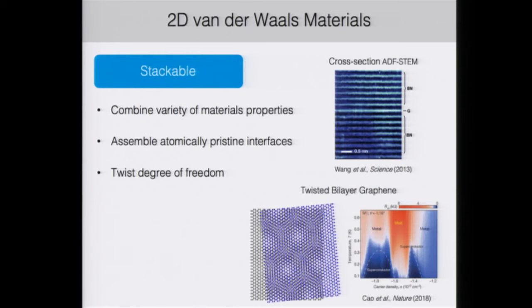So once you have a few properties that you want to combine, you can just stack them on top of one another with atomically sharp, precise interfaces. Here's a cross-sectional TEM of a boron nitride, graphene, boron nitride stack, and you can see that they really are atomically placed with one another.